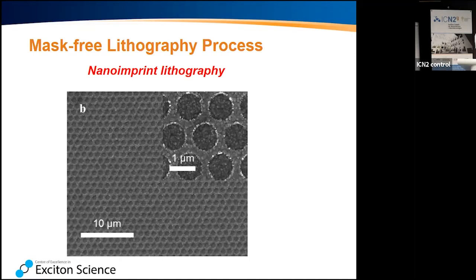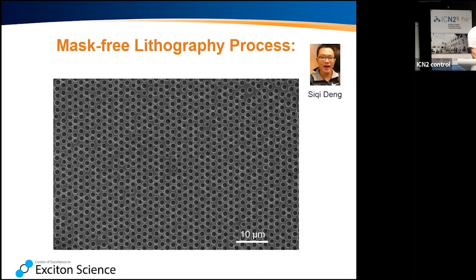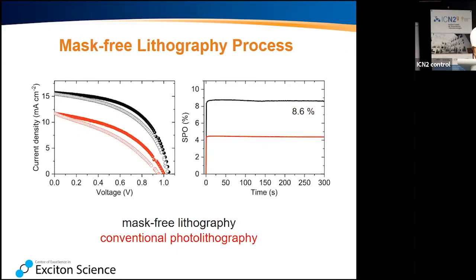And recently we developed an alternative method, and that was done by one of my PhD students, Siqi Deng. And you can see here now, this is a 10 micron scale, and you see how this beautiful regular array of kind of a back contact honeycomb structure. Efficiencies also have gone up here. We're comparing the current voltage characteristic of a conventional back contact solar cell made with photolithography to one that is made with this mask-free lithography method that we just developed. And you can see it outperforms it quite nicely.